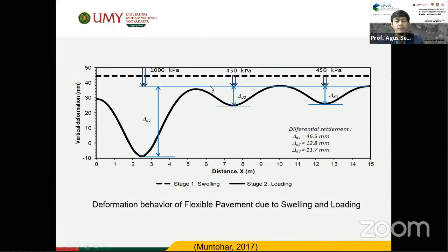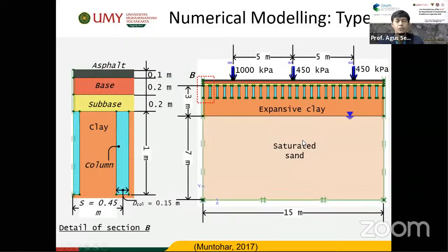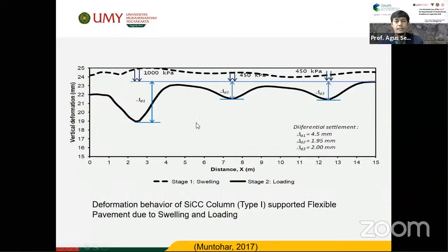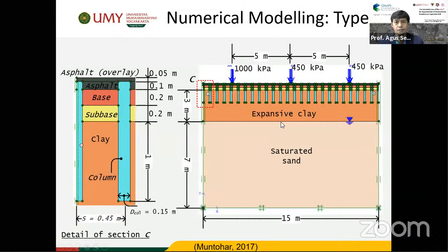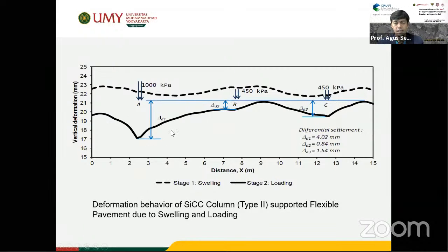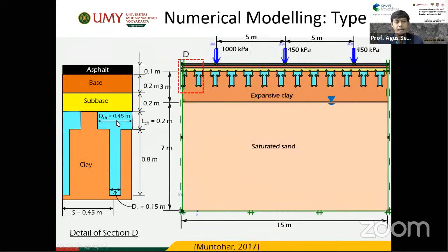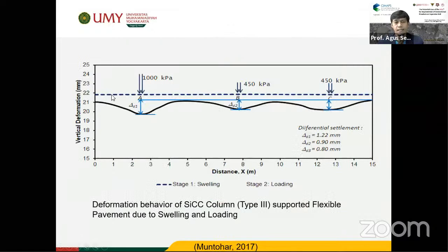If the flexible pavement is unsupported by the column, the differential settlement is larger. But after we install the column, based on our numerical modeling, the column can reduce the differential settlement. And also, if we install the column starting from the surface, it can also reduce the differential settlement of the pavement. But the swelling is still not uniform here. But if we use this method, type 3, where we enlarge the pile cap, you can see based on our model, the swelling is almost uniform on the soil surface, and the T-shape definitely reduces the differential settlement.